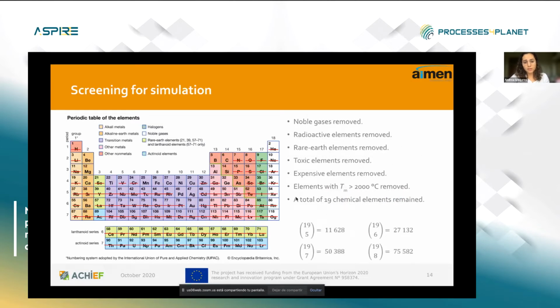But then we have done another screening. So we have removed also the rare earth elements, the toxic ones, expensive ones, just in order to not make it dangerous when manipulating them in the laboratory, and also because of costs. And then we have also removed elements with a melting temperature higher than 2000 Celsius degrees, because it is also difficult to deal with them in the laboratory. So finally, we have ended with 19 chemical elements to be possible parts of the high entropy alloys.